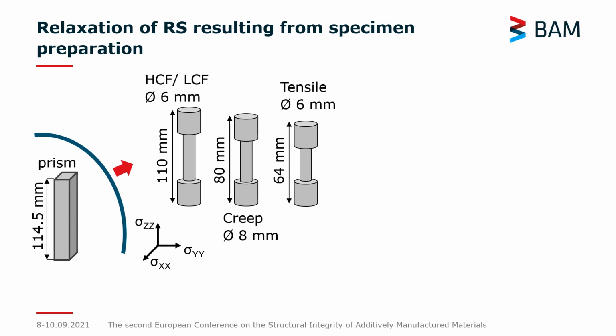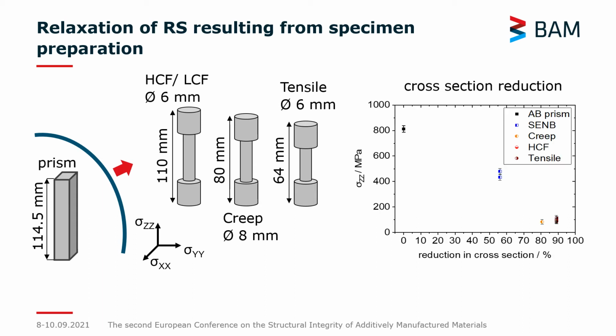And what we've observed is that when determining the residual stresses in the gauge section, so we have a heavy cross-section reduction compared to the prism, we see that independently of the height, the residual stresses are heavily reduced when compared to the as-built prism. So there's a very large effect on the stresses in the build direction. This also holds true for the other directions, if we go from, let's say, a larger specimen to a cylindrical specimen.